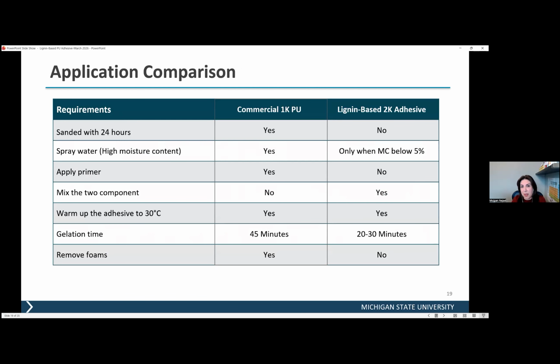Now let's try to compare this lignin-based two-component adhesive with the commercial one-component polyurethane adhesives. I mentioned some of the industry mass timber producers are still using two-component polyurethanes too, but this is based on the one-component that we compared in this study. For the commercial polyurethane adhesives, it's usually recommended that CLT producers sand or plane the wood samples that they're going to use within 24 hours, basically freshly sanded samples. We tested our adhesives even with samples that were planed or sanded three months ago. We still got good results. Therefore, we don't need freshly sanded wood.